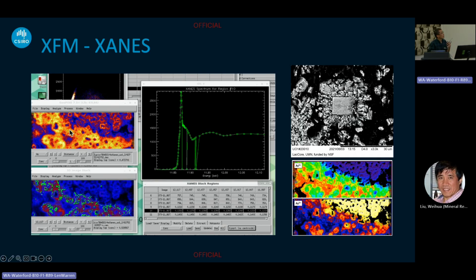So we did that. From the XRF mapping, we can see the ratios of different arsenic species in the minerals in situ. You can also plot, for example, arsenic 3+ versus arsenic 5+ ratios within those minerals to see how they evolve in those segments.